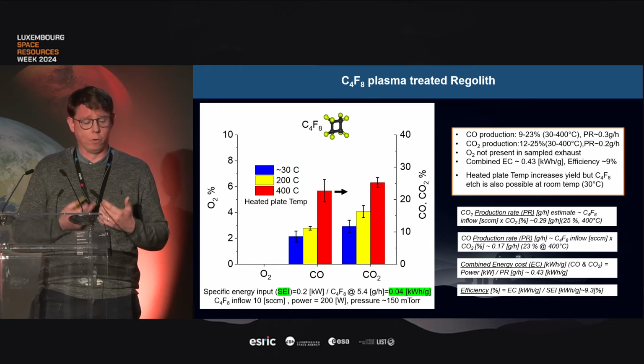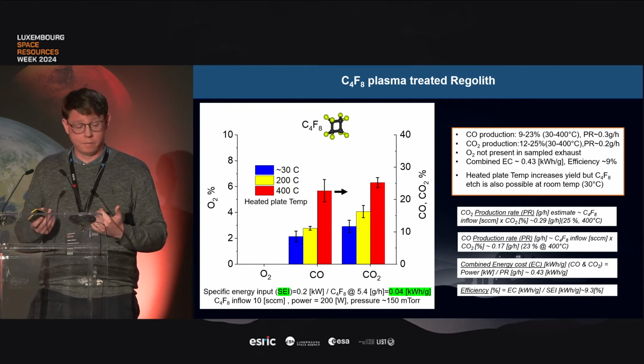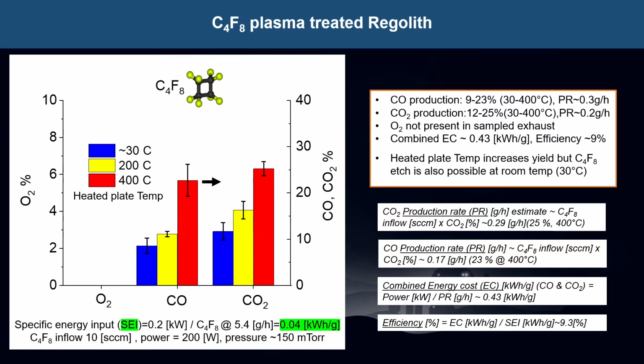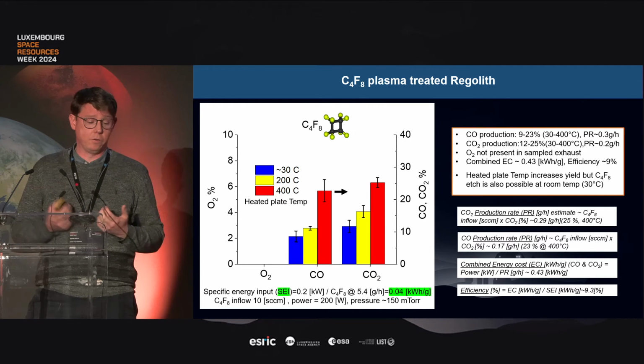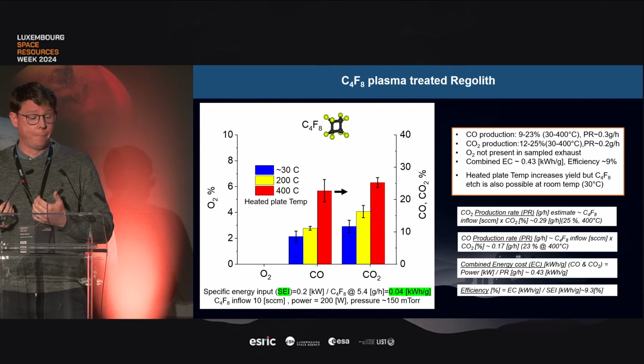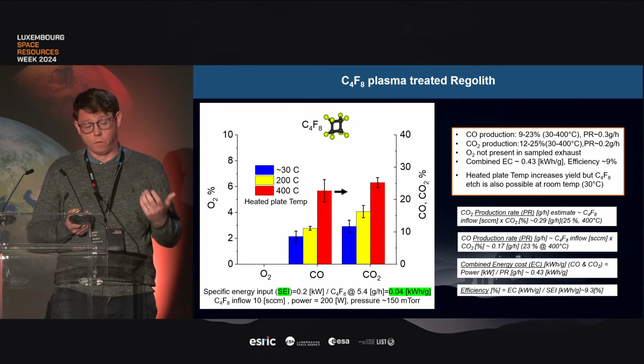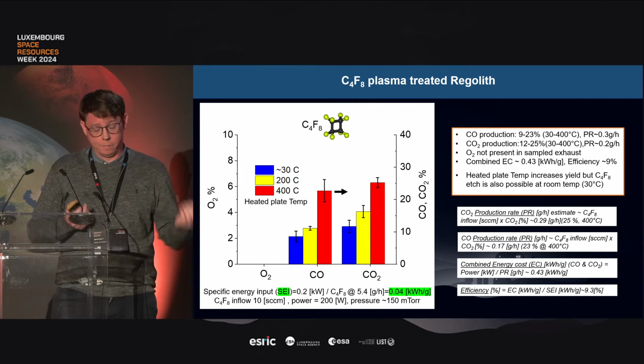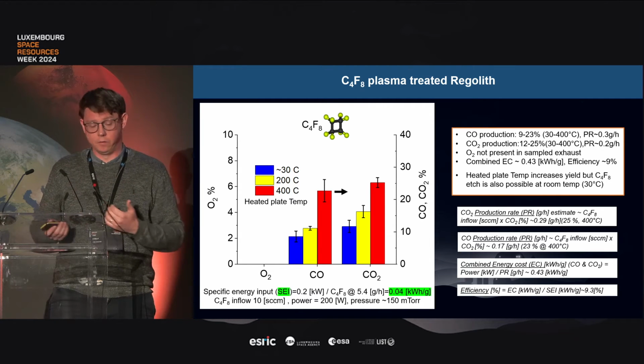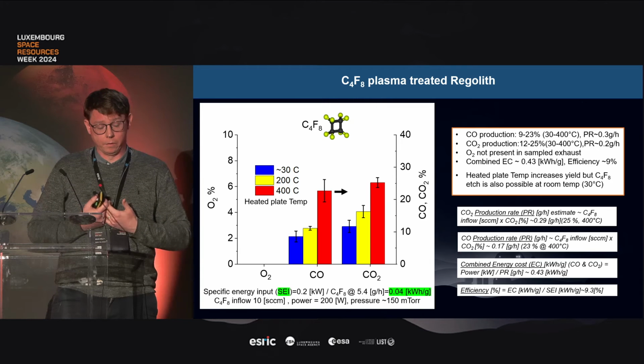We also see that the heated plate is playing a role in increasing the yield, but it is not necessary to have it. The ambient temperature within the reactor is enough to allow the carbon dioxide and carbon monoxide production. In terms of absolute values, we're measuring about 10 to 25% of the CO and CO2 in the exhaust. Production rates in terms of absolute values are about 0.5 gram per hour. So if we combine those two together, we can get an estimation of the energy cost. It's about 0.5 kilowatt hour per gram. So this is an order of magnitude increase over the SF6. Then looking at the specific energy and the combined energy cost, you can get an idea of efficiency. It's about 9%, so again, an order of magnitude increase.